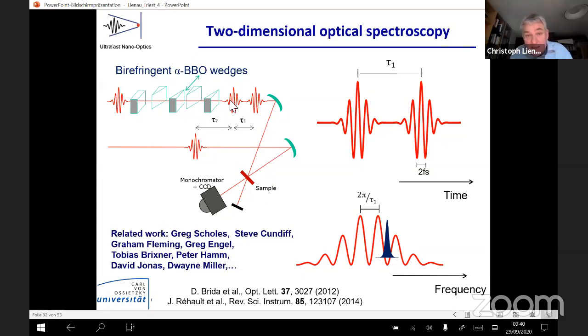In this two-dimensional electronic spectroscopy, what you do is that you do not just take a single optical pulse as the excitation pulse, but you use a phase-locked pair of pulses with a certain time delay. Let's call it tau1 here. This pair excites the system under some angle, and the second pulse probes the system, and the second pulse is time delayed by some time delay tau2. One also calls this the waiting time in the experiment.